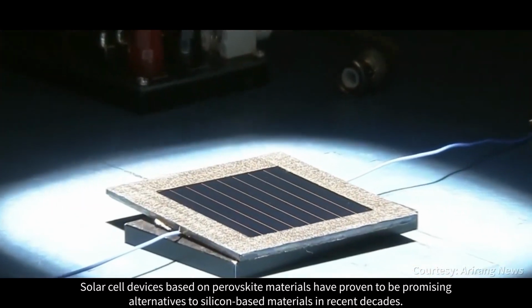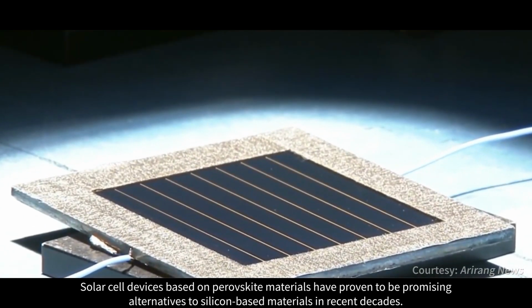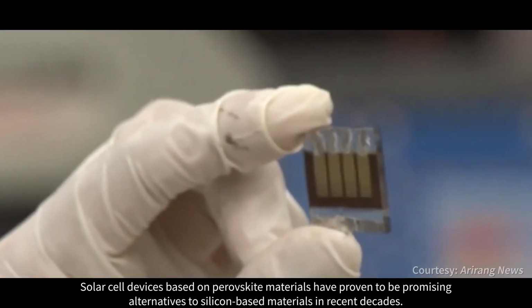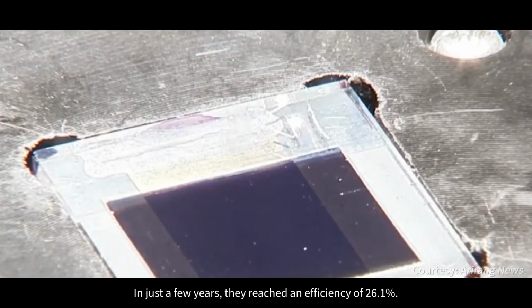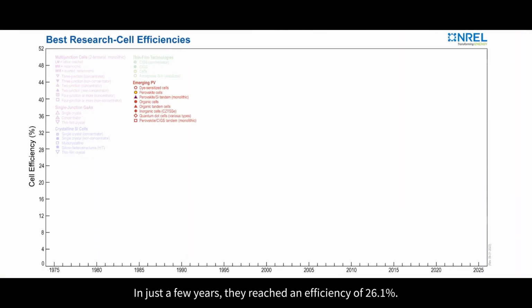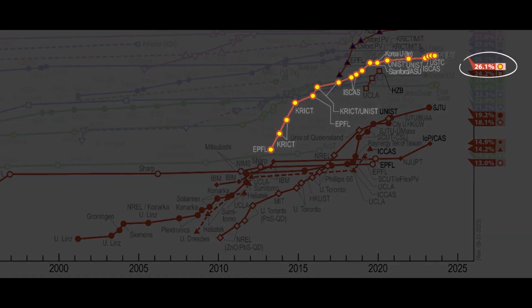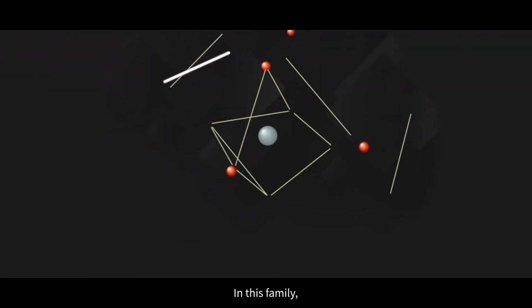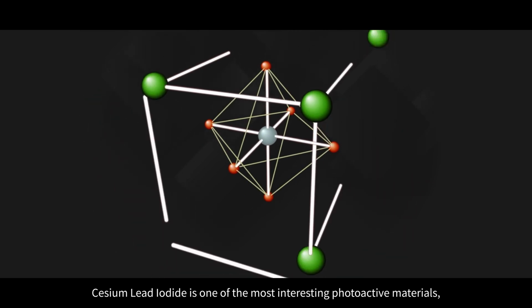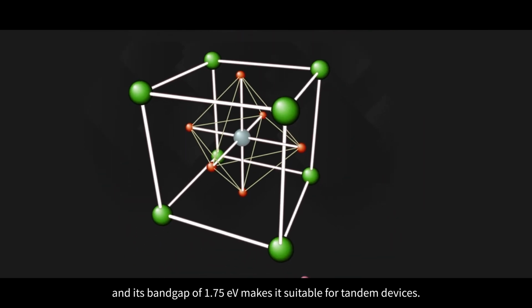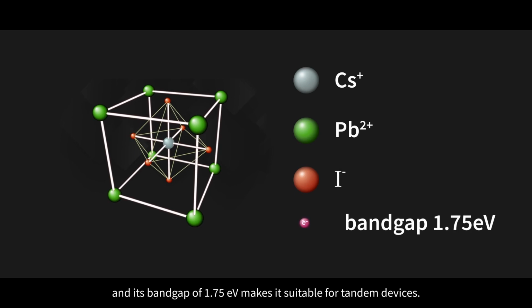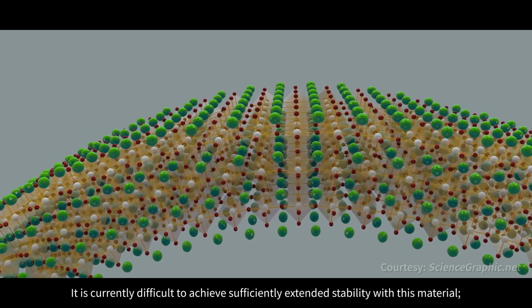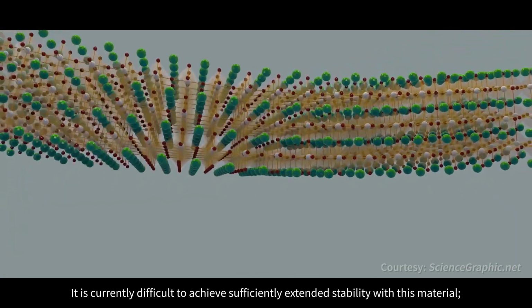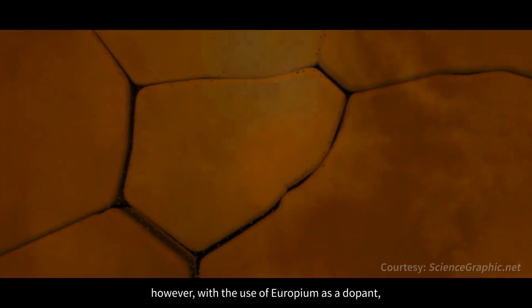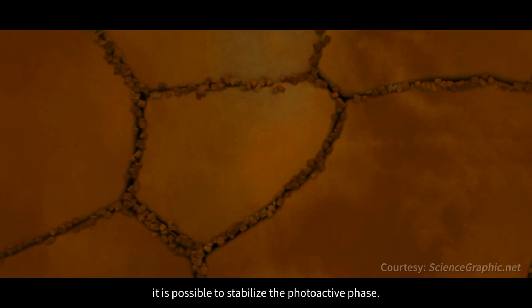Solar cell devices based on perovskite materials have proven to be promising alternatives to silicon-based materials in recent decades. In just a few years, they reached an efficiency of 26.1%. In this family, cesium lead iodide is one of the most interesting photoactive materials, and its band gap of 1.75 eV makes it suitable for tandem devices. It is currently difficult to achieve sufficiently extended stability with this material. However, with the use of europium as a dopant, it is possible to stabilize the photoactive phase.